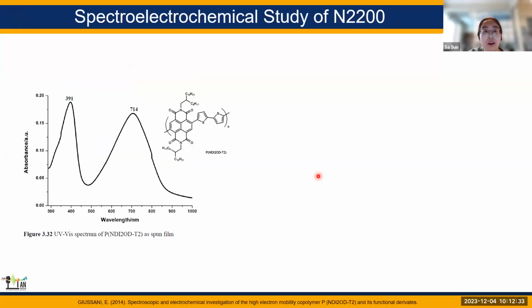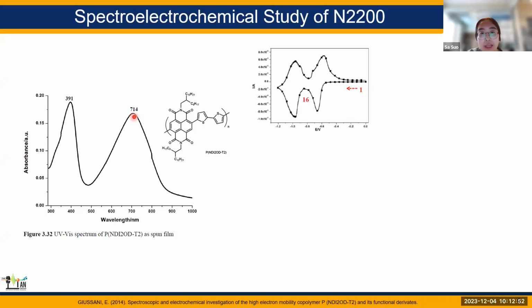And I'm gonna show you a spectroscopic study of electrochemical doping of N2200. So here shows the typical absorption spectra of neutral N2200. There are two major peaks at 390 and 714. In this experiment they use a gold electrode as the substrate, and the experiment is done in acetonitrile. So when they scan from 0 to negative 1.2 volts, they can see two reduction peaks.